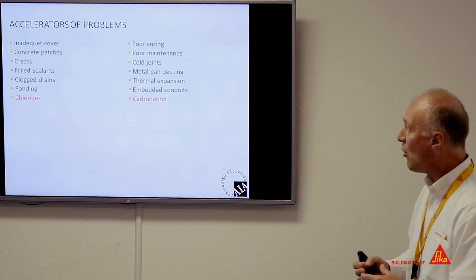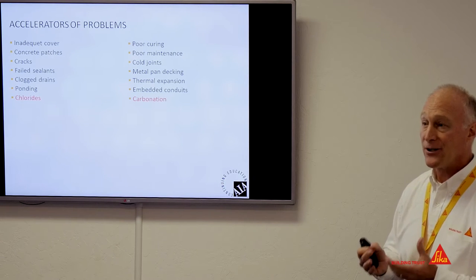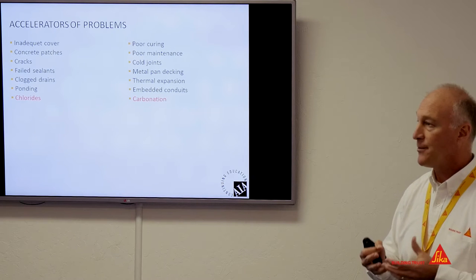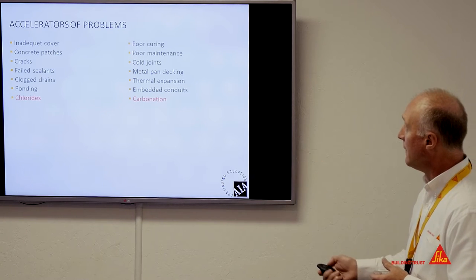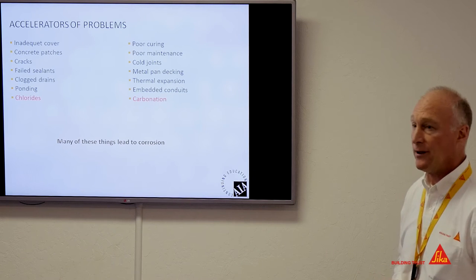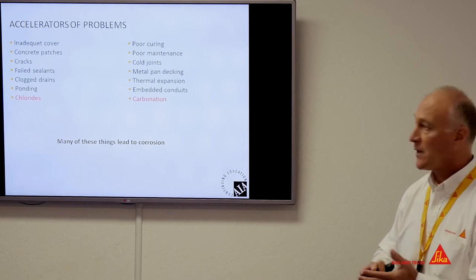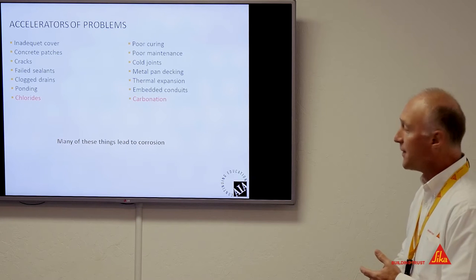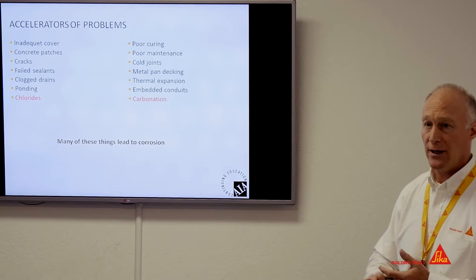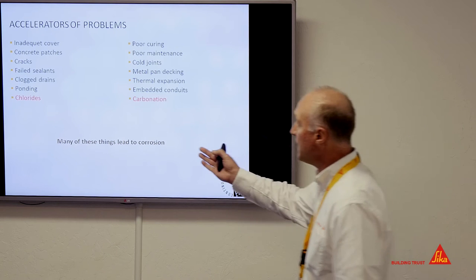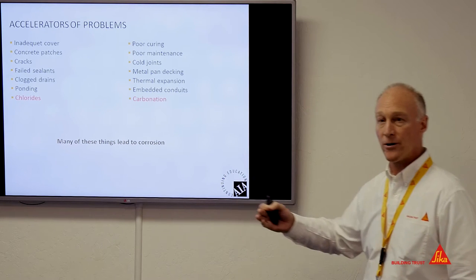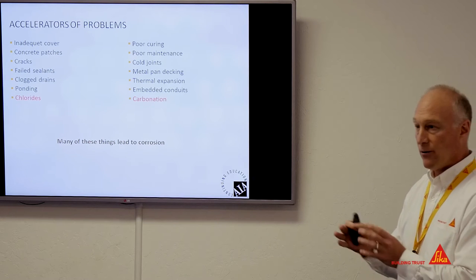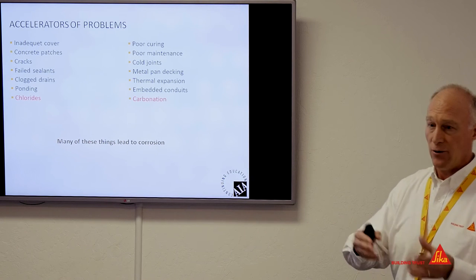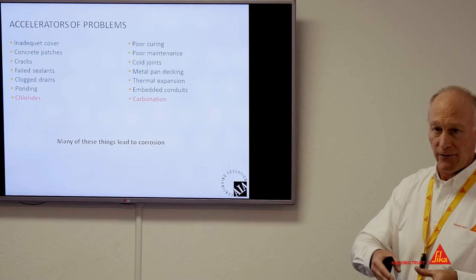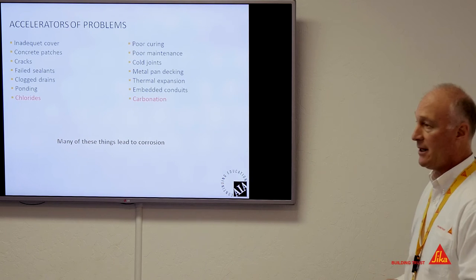These, I call them accelerators. They don't necessarily cause corrosion, but they are accelerators. They are contributing reasons as to why ultimately we're going to have corrosion. Whether it's inadequate cover or poor quality cover, previous concrete repairs, patches that aren't performing, failed sealants, clogged drains, ponding of water. All of these things lead to a condition that can cause the steel to corrode faster than it would have if these conditions were being addressed.